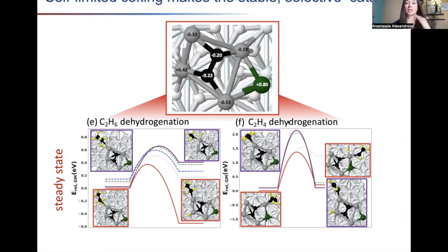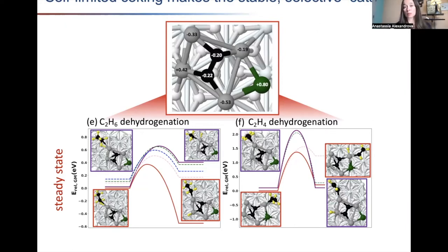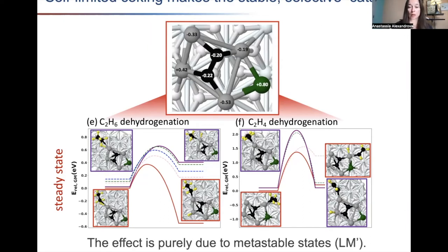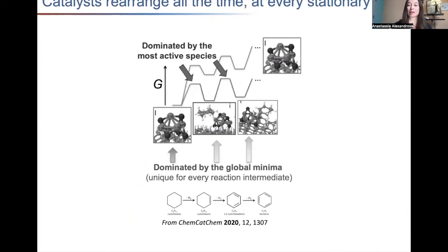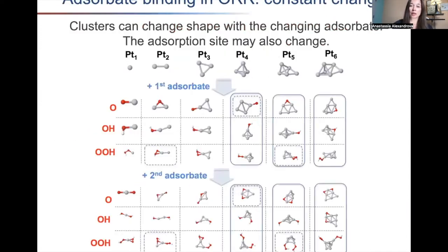This self-limiting behavior is due to a synergistic electronic relationship with germanium. Carbon is an oxidant — without germanium it would take electrons from platinum and affect its reactivity, inviting more coke. But germanium effectively donates electrons into the C2 unit, and platinum remains intact — just like the initial platinum cluster — which retains its activity, yet Pt4Ge does not dehydrogenate more deeply. So we form a self-limiting poisoning effect, discovered somewhat by accident.